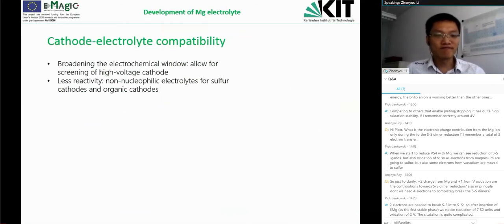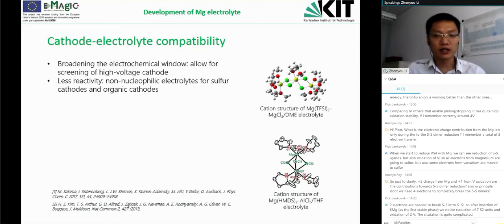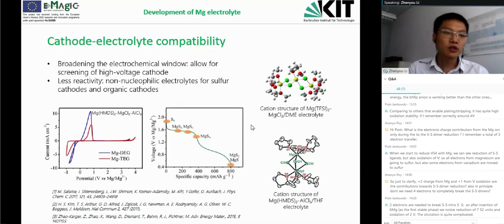But the limit is still that in the APC case we have a relatively narrow electrochemical window. This limits us from investigating magnesium storage in a high voltage cathode. Also, the nucleophilic nature of the electrolyte makes it incompatible with the sulfur cathode and also with the organic cathode. That's why several non-nucleophilic electrolytes have been developed. For example, magnesium TFSI with magnesium chloride, as highlighted by Professor Aurbach, and also the magnesium HMDS electrolyte, also in combination with aluminium chloride. From the CV, we can see extended oxidation stability up to 3.5 volts, which is much improved compared to the APC case. And as demonstrated in the magnesium sulfur cell, it is compatible with electrophilic cathode materials.